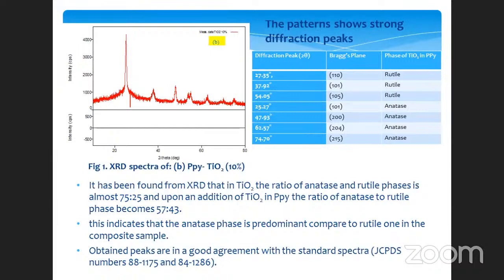These are the results which we have obtained from polypyrrole and TiO2. Here we can see that the first three prominent peaks at 27 degree, 37 degree, and 54 degree are of the rutile nature of this TiO2. But when this pure TiO2 is added and composed into the polypyrrole matrix, it changes. Three peaks are of rutile and four peaks are obtained of the anatase phase.